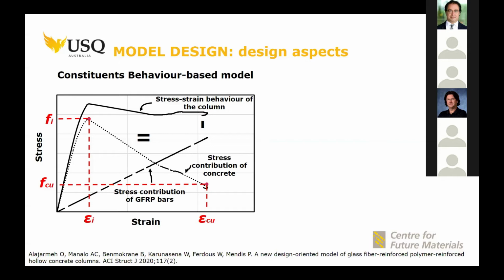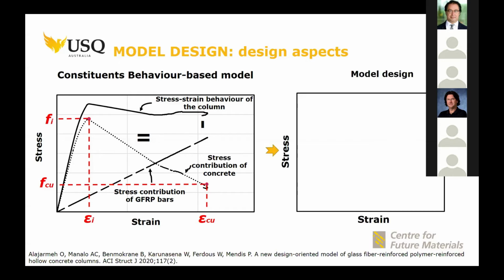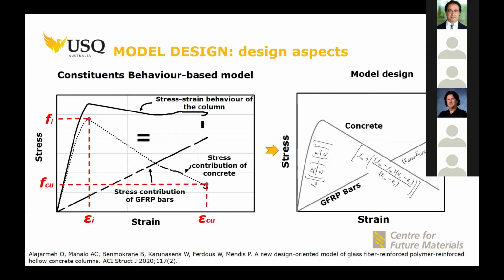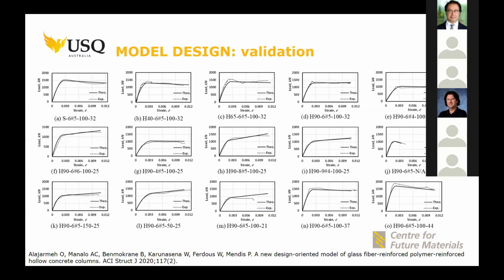We used this theory with the experimental data that we have to initiate some relationships to find these peaks and their locations. The model design is based on modeling the concrete itself by dividing its behavior into an ascending line and a descending line, all based on the experimental design parameters. Then, by taking the linear elastic behavior of the GFRP bars and combining them together, we can find the total behavior of the GFRP reinforced hollow columns. And applying the same theory for the whole columns, we found ourselves validating this model with all of the experimental data that we have, with a good agreement.